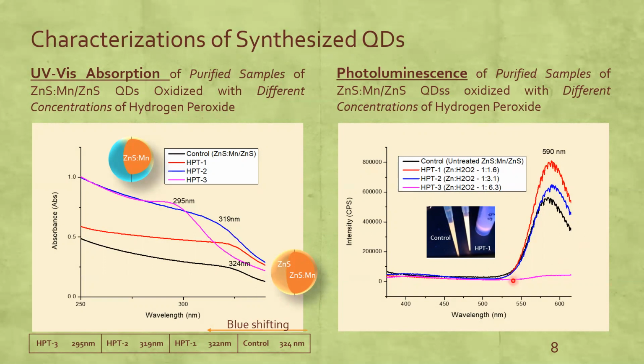Here we study their fluorescence. The data is taken with concentration adjusted so we can compare their intensity. This is what we visually see under a UV lamp. The orange color fluorescence is due to the manganese dopant and corresponds to an emission peak at 590 nanometer. The least peroxide treated sample, HPT1, is showing higher fluorescence than control. We also confirm this in the spectrum, where we see that HPT1 and 2 both show higher fluorescence than control, whereas for HPT3 the manganese emission peak has completely quenched.